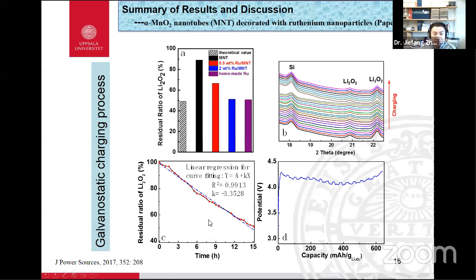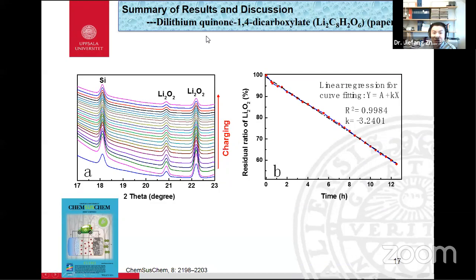This is another example, ruthenium deposited on manganese dioxide nanotubes. We get a similar result. This is another example, a quinone-based organic catalyst in the cathode for the lithium oxygen battery. You see this matches the theoretical curve. This just depends on the amount of catalyst that you used. The important thing is you compare the same amount of different catalysts for the effect.